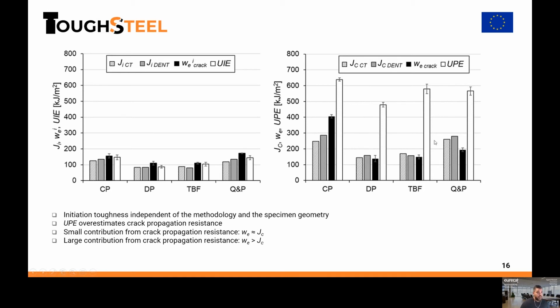Now, comparing this essential work of fracture and JC values, as I said, often in the literature it is assumed that JC and essential work of fracture are equivalent. We can see, for example, that when there is no large contribution from crack propagation resistance, that is to say, when the essential work of fracture is close to the initiation toughness values, these JC values, the green bars and the dashed bars, can be more or less equivalent to the specific essential work of fracture. CP, DP, TBF, Q&P here.